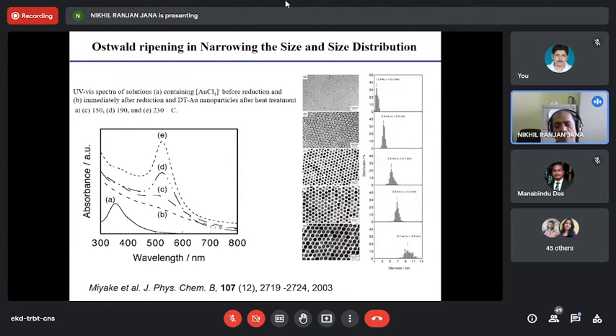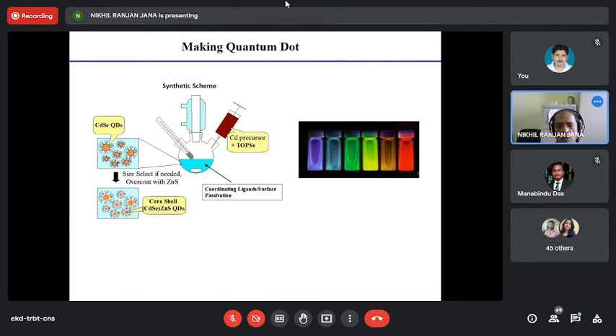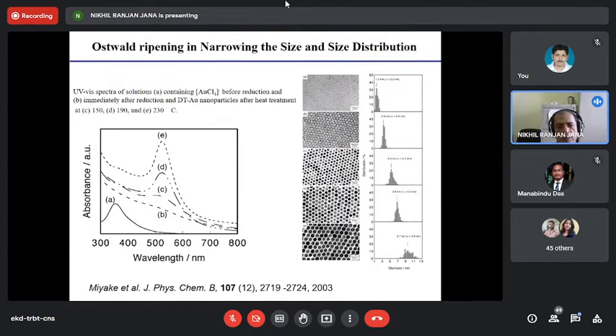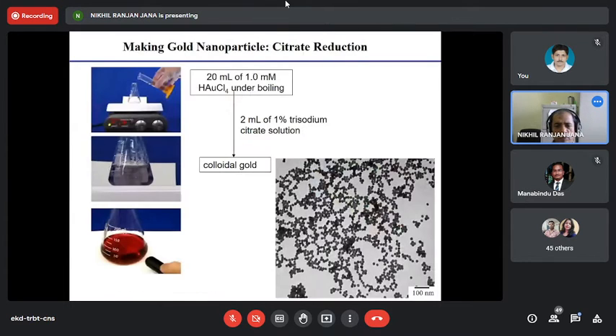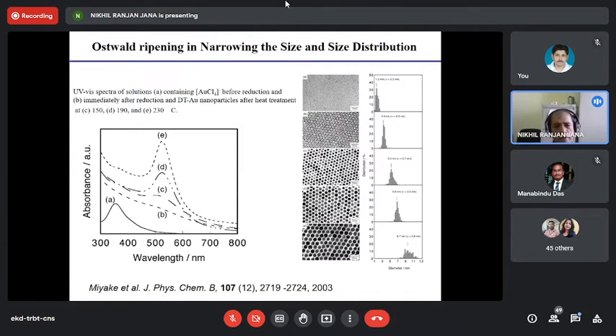Making gold nanoparticles. This one, we made gold nanoparticles of 10 nanometers. If you want to make them smaller than 10, there is another very beautiful, powerful approach. What is that? It's a thiol-based surfactant. First, make dodecanethiol-capped gold nanoparticles, which are very small, 1 to 5 nanometers. Very similar process, but instead of water, we use an organic solvent-based approach, where gold nanoparticles are kept with a dodecanethiol surfactant. These are 1 to 3 nanometers.